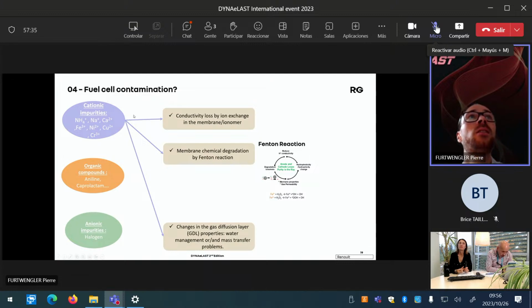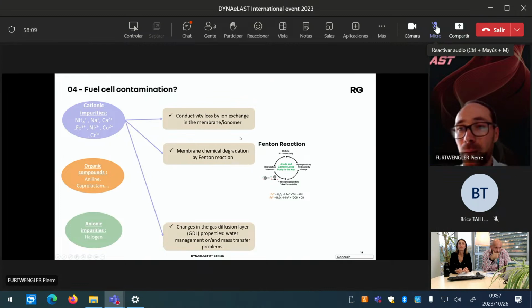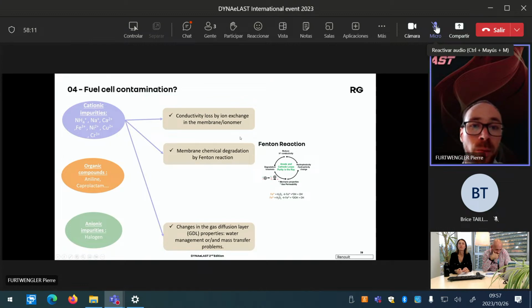And one cationic impurity that we really don't want is the 3+ oxidation state, because this one is the only one which can create a degradation which is not reversible. If you have a contamination of the catalyst or a contamination of the membrane, you can imagine that you can wash it and recover your fuel cell. But with the ion in 3+ oxidation state, you will initiate the Fenton reaction on the membrane. So the membrane is degraded, and so you are really losing your fuel cell for the first time. So it is really not good.